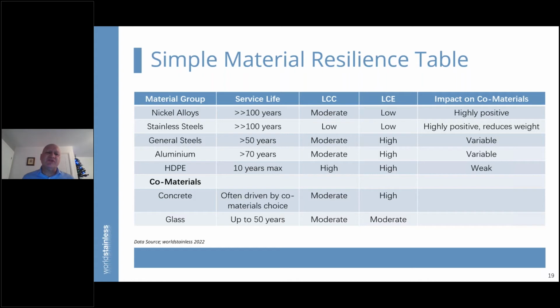If you want to reinforce concrete, you're probably going to choose a steel of some sort. And there's differences. If you choose stainless steels with its very high strength, particularly the duplex stainless steels, you can reduce the weight of concrete. So you have another impact, a knock-on positive impact, which is really good. General steels just fall a little bit behind, but still can have a positive impact there. So this is about thinking about your materials and their impact very carefully.